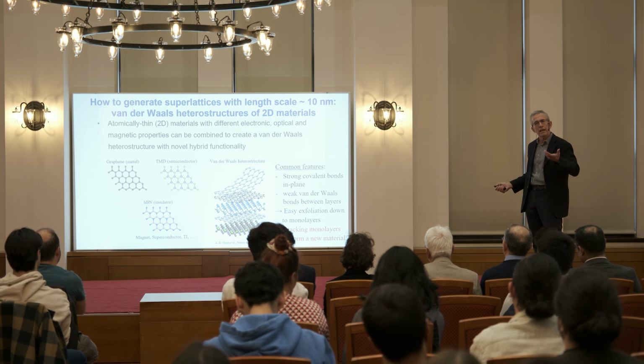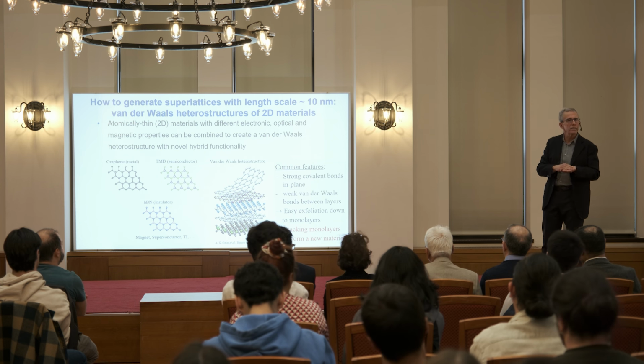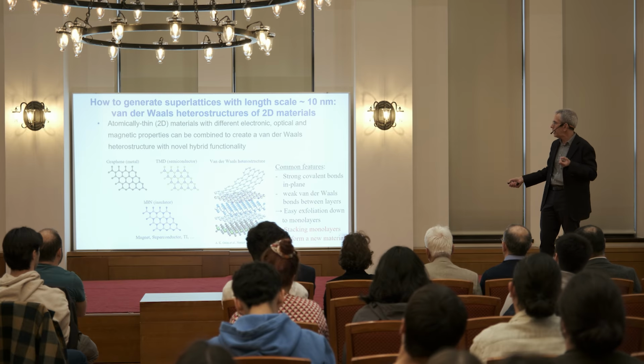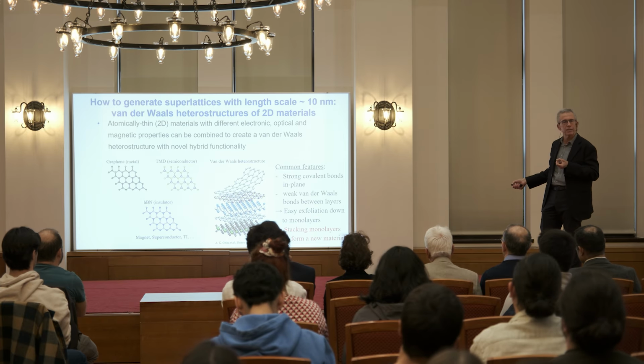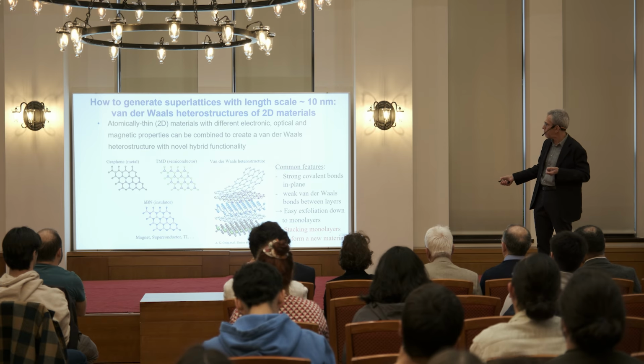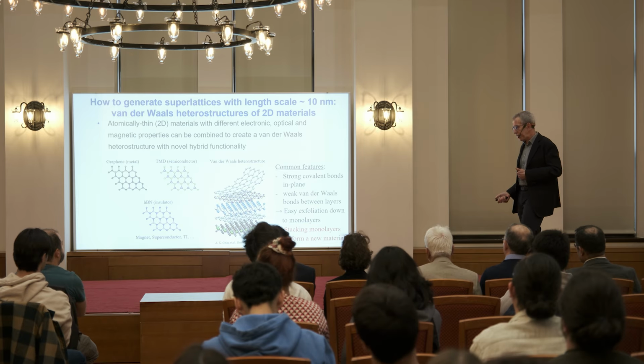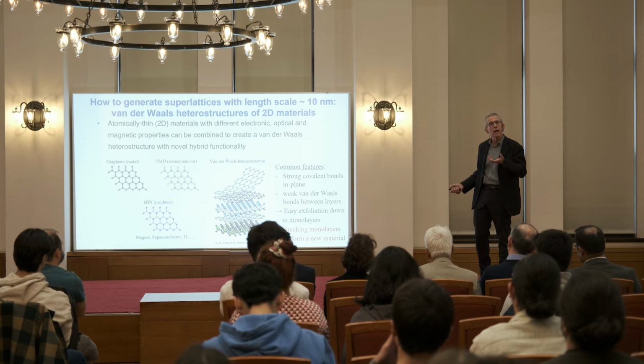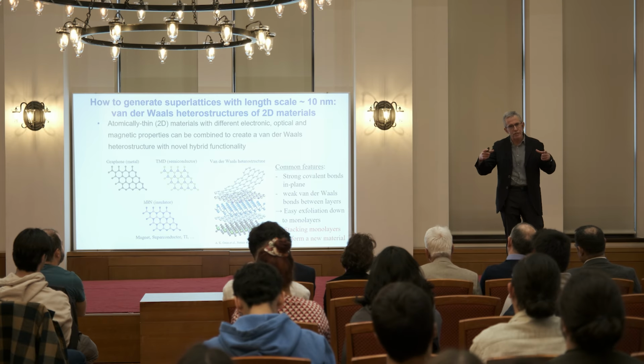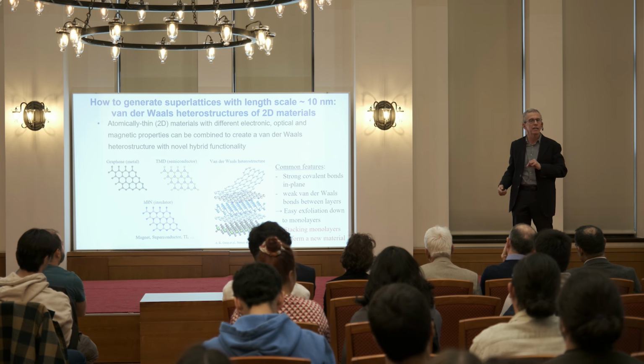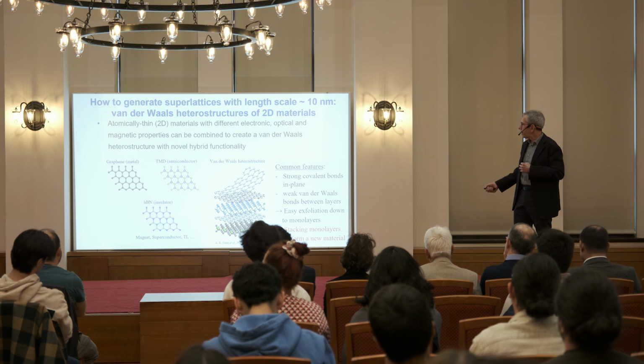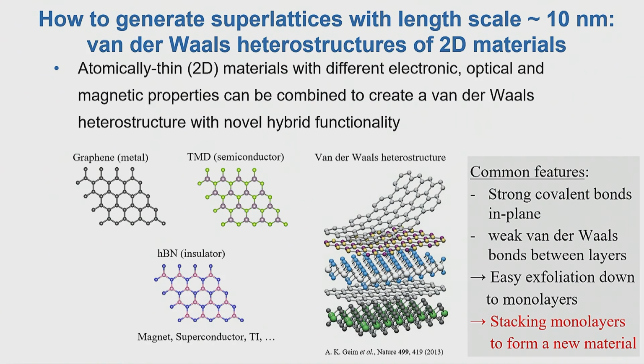So what that means is that it is very easy to peel off layers and go down to essentially a material that is a single atom thick. So this could be graphene, which is a semi-metal. Upon exfoliation with low-tech tools like Scotch tape, you can create structures that can be 100 microns in size, and that are literally single atom thick sitting on a substrate. And there are all kinds of other materials. There are insulators, boron nitride, semiconductors, the transition metal dichalcogenides, which I'm going to talk about. And then you can also stack them up to make a new van der Waals heterostructure with new functional properties.